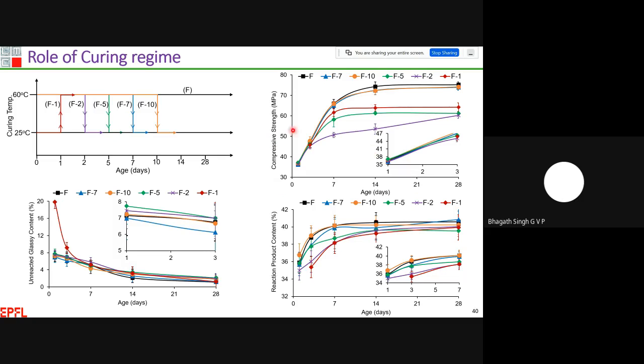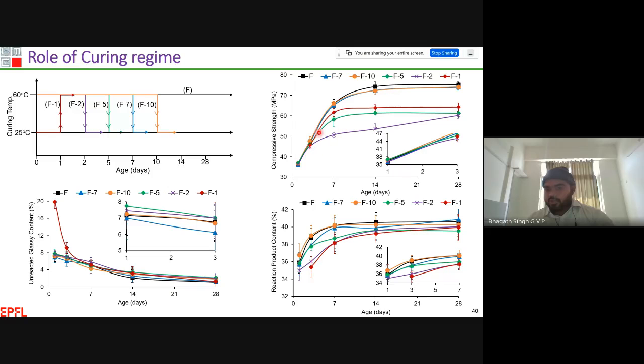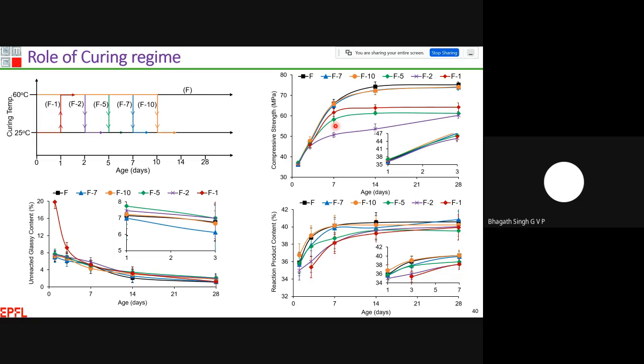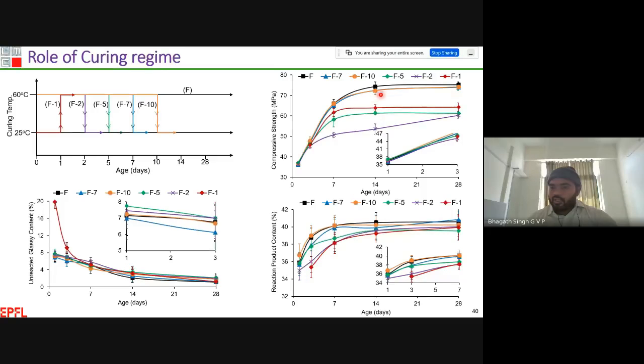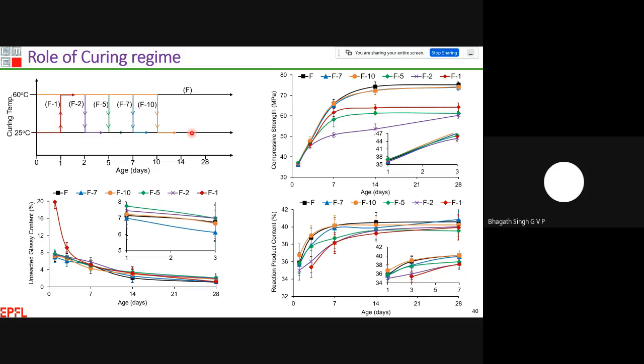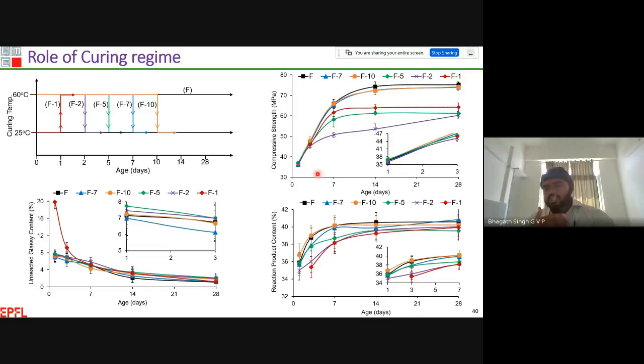As you can see here in the compressive strength, this is the baseline mix, F, which is completely cured at 60 degrees Celsius. As you observe here, for F2, F5, and F1, whenever we raise the curing temperature, there is a rapid increase in the compressive strength. But in the case of F10 as well as F7, the fly ash was cured at 60 degrees Celsius for 7 days, followed by 25 degrees Celsius. After seeing all these results, when using it in concrete, the fly ash alkali-activated system should be cured for 7 days at 60 degrees Celsius. Then only can you achieve the maximum compressive strength without increasing the curing temperature.